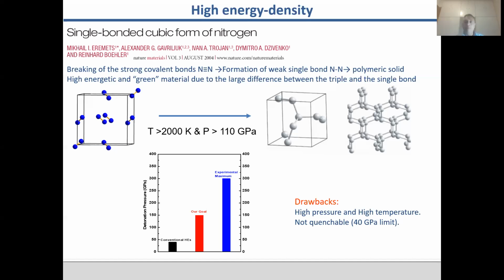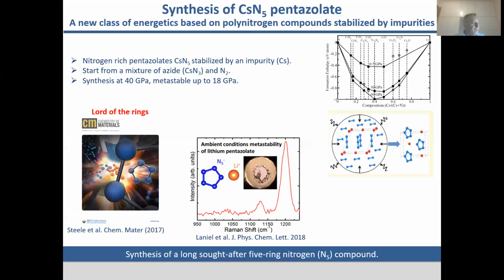Everybody, okay, 90% of people in this field start from azides, and the cesium pentazolate, and mix it with nitrogen. The reason we chose cesium instead of other alkali metals was just practical, to help us in the X-ray diffraction. So as you may see in the convex hull, these pentazolates become stable at about 30 GPa. And indeed, by just mixing the azide together with nitrogen, we managed to synthesize this compound at about 40 GPa.